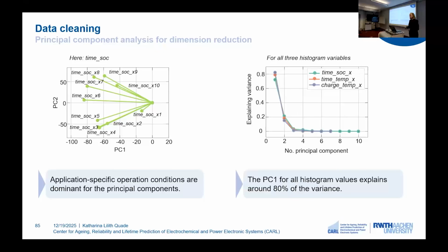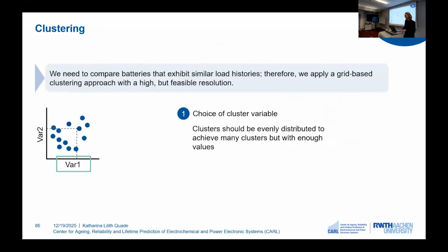And we can now also have a look for all 3 variables at the explaining variance. Here we have all possible principal components on the x-axis and on the y-axis the explaining variance. And we can see that for all aggregated values, we have roughly 80% of explaining variance, which is quite acceptable. We can see that with the principal component 2, we have an additional 20% explaining variance. However, we stick with principal component 1 and have reduced now our histogram variables to 1 principal component variable. This means we can now proceed with the clustering of our cells because we want to account for different load histories. And that's why we adopt a grid-based clustering approach.